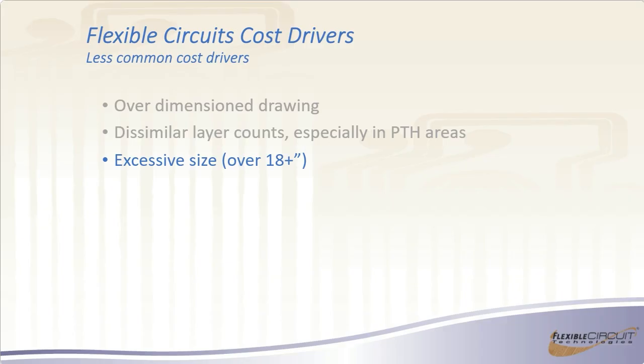There's other things, like as you remove copper from our pre-clad laminates, the laminates will shrink. So you may lose some of that up front, and then if you get humidity, it may grow back into tolerance. So lots of things can happen, and we're pretty good at predicting what's going to happen after all these different processes. But like I said earlier, if you have a critical dimension, put it on the drawing. If it's not critical, remember it's flexible, and just let the circuit be flexible and take up that dimension.